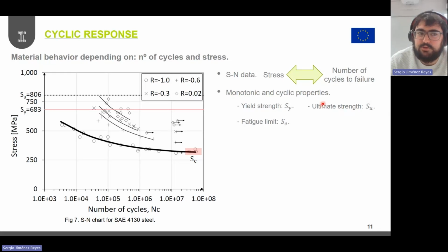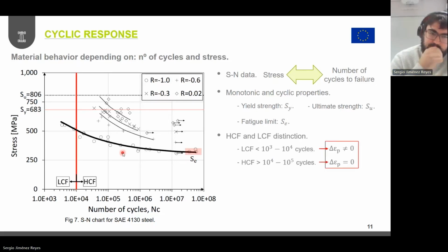We can also point out the ultimate strength, and we can also compute in a certain manner the fatigue limit, below which no fatigue degradation is expected. And it is also typical for this type of information to distinguish, as I was commenting previously, two regimes for the fatigue response in a material: what is called low cycle fatigue and high cycle fatigue.